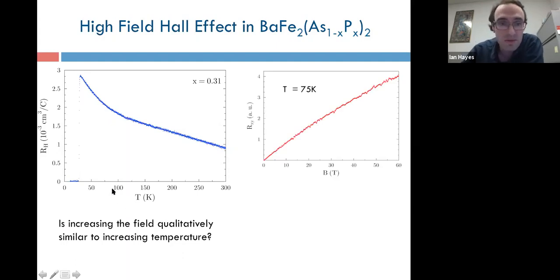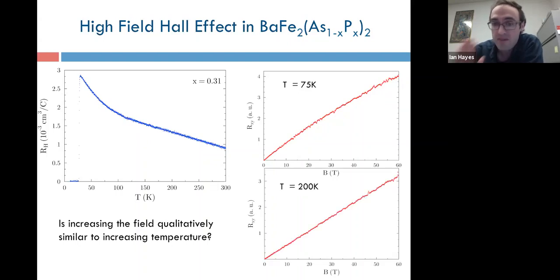So if you go to the middle of that upturn, somewhere around 75 Kelvin, and measure Rxy, the off-diagonal resistance, as a function of field, you'll see that it's actually sublinear. So if you were to define an effective Hall coefficient at each field, that's Rxy over H, say, then you would actually see it's decreasing with field, qualitatively similar to what happens when you increase temperature. And furthermore, this only happens within this low temperature upturn region. So if you go up to 200 Kelvin, you get a very straight Rxy all the way up to 60 Tesla.